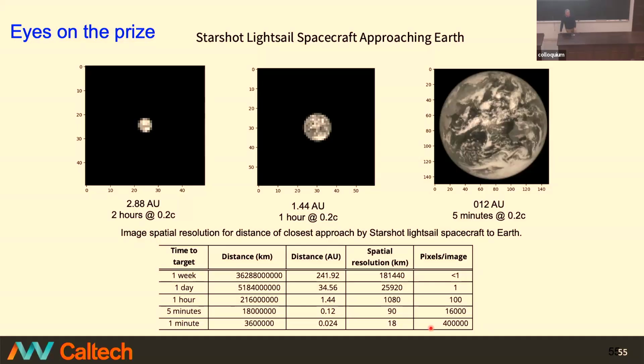Well, okay. So I guess one thing we know, it doesn't have to be single crystal. In fact, the silicon nitride is amorphous. We can deposit very uniform amorphous layers. In fact, my colleague Richard Norte at Delft University has built light sails at the 50 millimeter scale and is testing them. So we are not the holders of the record of the largest structures. So I'm pretty confident we can do that. And frankly, if you end up with a defect that induces anomalous absorption, it will just blow a hole in that region of the light sail and heal itself.